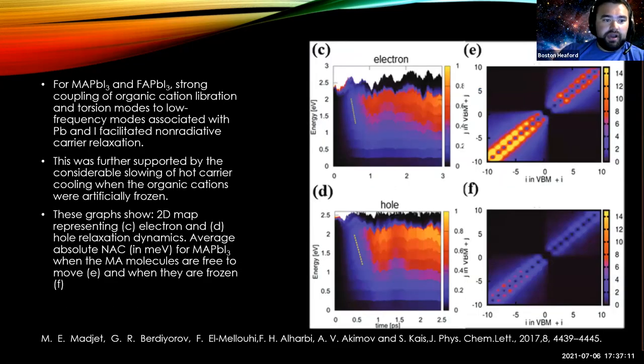And so for the methylammonium and again, FA, I struggle to remember that name. The strong coupling of the cation libration and the torsion modes to low frequency modes associated with the lead and the iodide facilitated the non-radiative relaxation. And this was further supported by the considerable slowing of hot carrier cooling when the organic cations were artificially frozen, which is shown on the right.